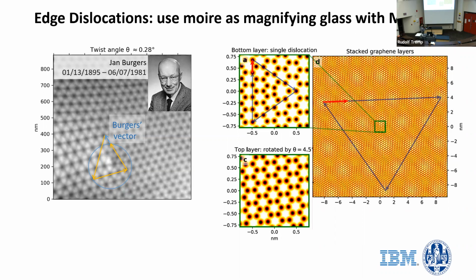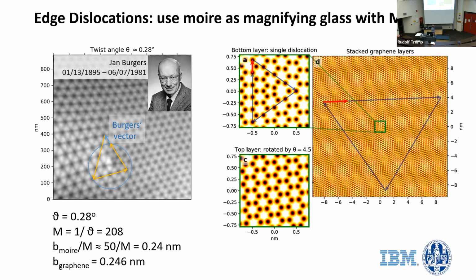Now, the Moiré pattern functions as a magnifier with a magnification of 1 over the rotation angle. The rotation angle is 0.28 degrees. So if you take this Burgers vector, 50 nanometers, divided by 1 over theta, so we divide by 208, you get an atomic scale Burgers vector of 0.24 nanometers. And for graphene, we expect a Burgers vector of 0.246. So this very simple method allows us to see dislocations in this bilayer structure, even though our real space resolution is not nearly enough to do it. But we have this fortunate effect that the Moiré lattice acts as a magnifier for what happens on the atomic scale.